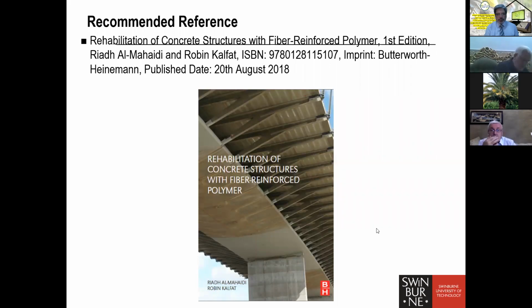The other issue is wetting and drying, humidity. We have done an extensive amount of work by way of accelerated testing, exposing the FRP, the epoxy and the concrete, while they are loaded, to cyclic humidity and cyclic temperature variations. We found that the maximum degradation we get in the bond was in the range of 15 to 20% under the most severe conditions. That we introduced as part of the CE, if you recall. One of the equations had a CE, the environmental factor. So for any heavy exposure, we use reduction factors to ensure that we have the capacity reduction well covered. So that's as far as that is concerned.